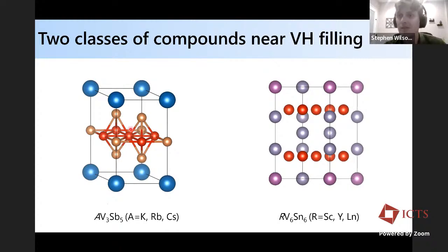realizes primarily an in-plane breathing mode of the Kagome net, whereas for the one on the right, the lattice instability is primarily a chain instability out of the plane. And so I'll talk to you about different flavors of interesting charge correlations that form in these systems, which are also connected to the Kagome sublattice in each system.